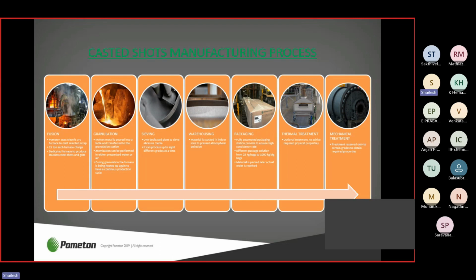Again, it goes for a mechanical treatment, which again is not for all grades of stainless steel sorts. This process is mainly for the stainless steel grades where the hardness has to be very high, like 55 to 60 HRC, and where the shape of the grit has to be angular, not round, so that it can work very aggressively to remove scales from forging parts and other surfaces where the scaling is very hard to remove. So mechanical treatment is mainly for grit, where we change the shape of the sorts into angular grit and increase the hardness, close to 60 HRC. So this is the whole process for casted sorts of stainless steel.